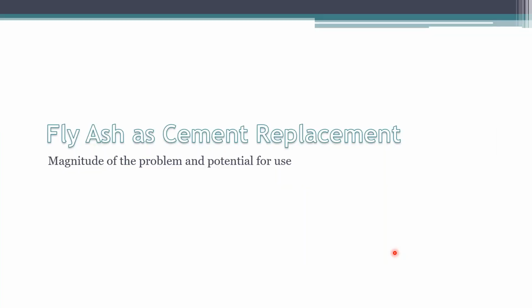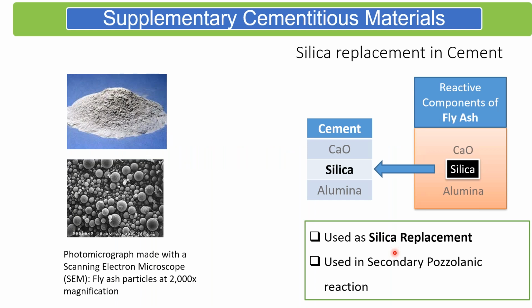So I'll quickly talk about fly ash as cement replacement. And in the India specific scenario, I believe this is one of the key things that we need to look at, because for us, fly ash is something that is available in abundance, at least for the foreseeable future. And the whole point here is that when we look at fly ash, it has lime in a low quantity. Primarily, it has silica and it has alumina. And when I look at cement, that also has lime. Of course, here it has abundance of lime, silica, and alumina.